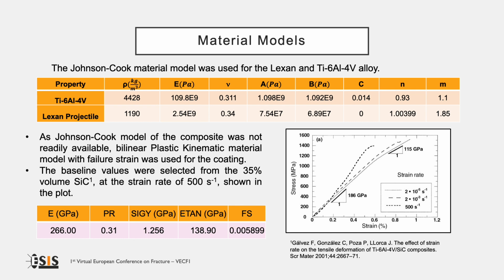This material model takes into account strain hardening, strain rate hardening, and thermal softening of the material. It is therefore well suited for the simulation of the material response under the condition of hypervelocity impact, where there are high strain rates and local heating. It was not possible to find Johnson-Cook parameters for the coating. Therefore, the bilinear plastic kinematic material model was used.